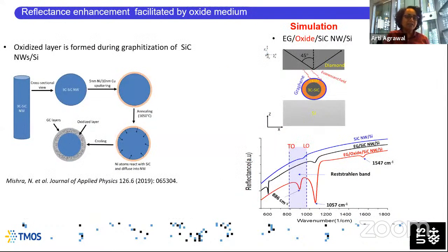Now, what we realize is that when we are graphitizing the nanowire, there is also a very thin layer of oxide that gets formed. That is what is shown here on the left diagram. You have the blue silicon carbide region with a very thin gray oxide layer. And then at the outer side of the oxide layer is the single monolayer or bilayer of graphene. When we simulate this particular structure, with silicon carbide at the center, then an orange oxide layer, and then this thin blue layer, which shows the graphene, we find that the red curve that we get is quite close to what was obtained experimentally.